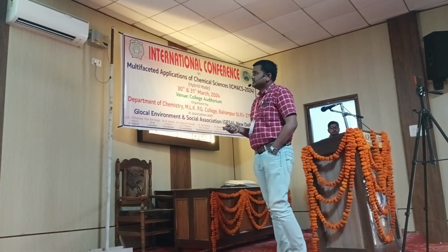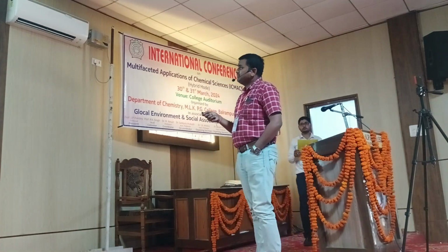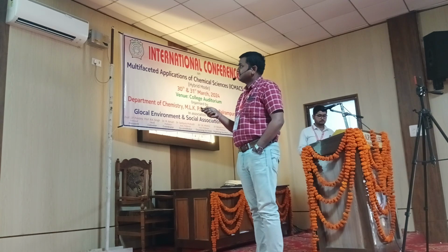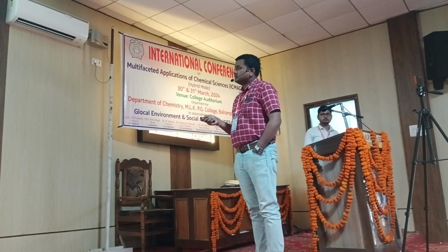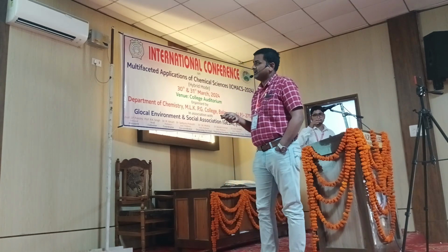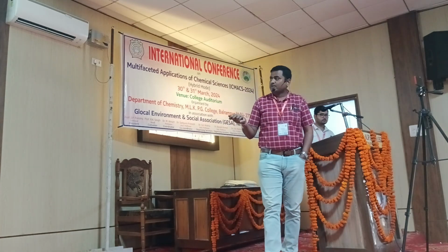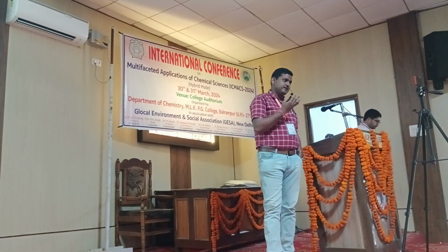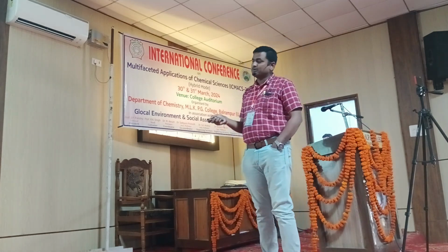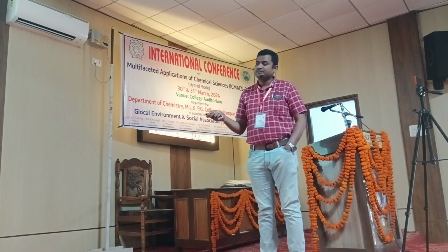Next, this J aggregation study has been further verified by lifetime analysis, and we found that the fluorescence lifetime of the monomer is greater than the lifetime decay of the J aggregate. So we confirmed the proposed hypothesis by fluorescence lifetime and zeta potential measurement, because the zeta potential is coming around 0, which suggests the formation of aggregates. There is no net positive or negative charge on the graphene quantum dots because of the electrostatic and hydrogen bonding interaction, so the zeta potential is almost 0.